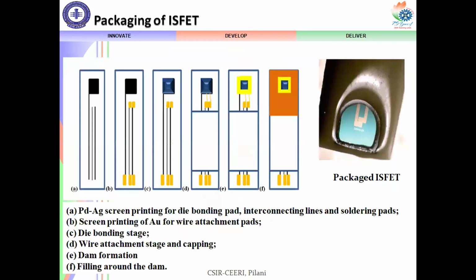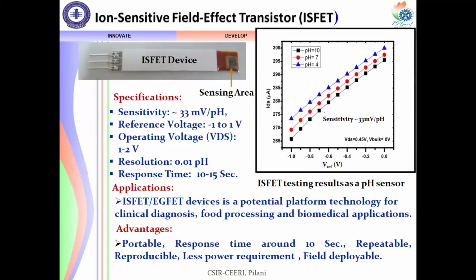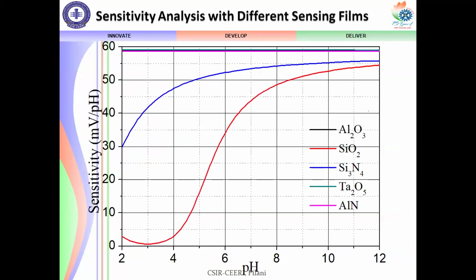This is the packaging of the ISFET, and this is the pH testing of the ion sensitive field effect transistor. So these are the different materials, as I said, that we have developed, aluminum nitride as well as tantalum pentoxide. We have simulated, fabricated and tested all these materials for pH sensing applications, where we have seen that aluminum nitride and tantalum pentoxide materials have better stability for the entire pH range.